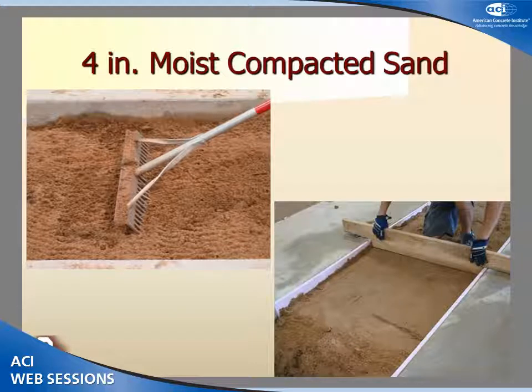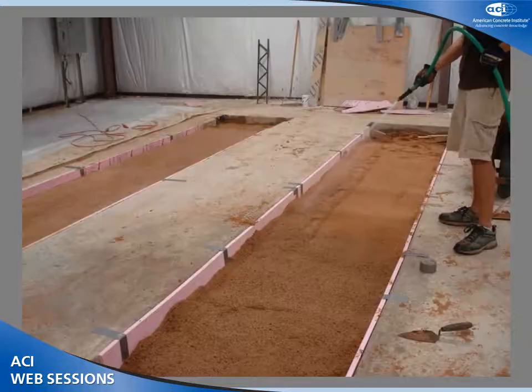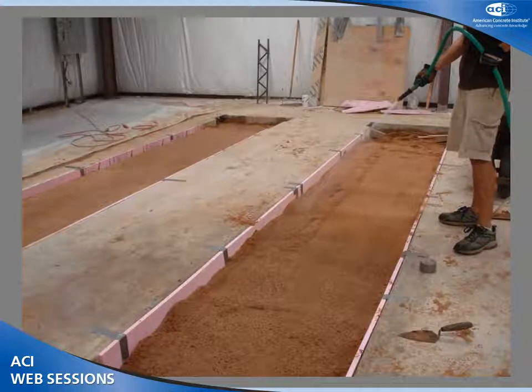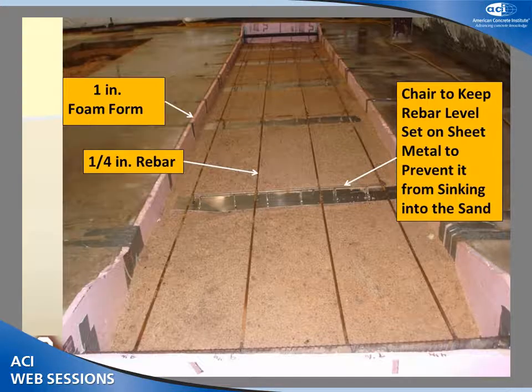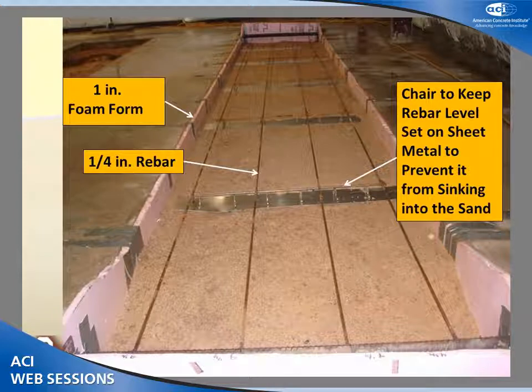Our slab specimens were located on 4-inch moist compacted sand. This picture shows the compacted sand, and here is wetting the sand. This picture shows a slab bed ready to be filled with concrete, and you can see the bars and the chairs we used to keep the rebar level at 1.5-inch depth of the slabs.